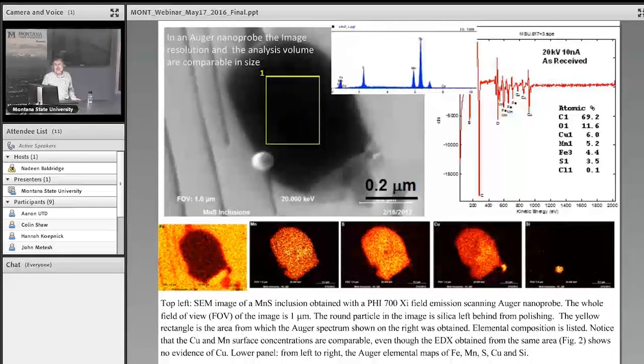And then we map. That's something that we do quite a lot. It's a fast mapper. You can do nanoscale mapping. It's spectacular. So we map iron. Okay, so there's more iron and less in the manganese sulfide. That's expected. Manganese should be there. It's manganese sulfide. Sulfur should be there, no problem. Copper shouldn't have been there, but it's there. I see copper right there. And in fact, this location right here has more copper, like in this corner, more copper there.